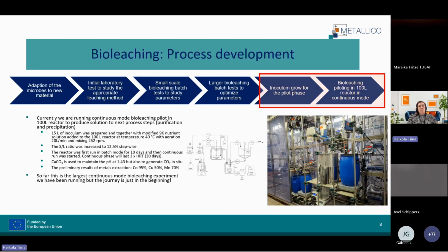And then the final stage. At the moment, we are running the continuous mode bioleaching pilot in a 100 liter reactor to produce solution to the next process steps, which are purification and precipitation. So for that, we prepared a 15 liter inoculum, and then it was added to the 100 liter reactor together with the modified 9K nutrient solution at 40-degree temperature with aeration of 20 liters per minute and mixing speed of 252 RPM.